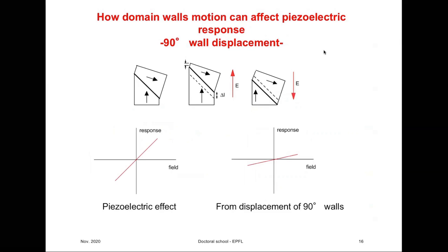Well, I'm exaggerating a little bit here the deformation of the crystal. The two domains are never at exactly 90-degree angle between polarizations. It comes from geometry, I'm not going to go into that. You have seen the pictures that I have given before of high, atomic resolution domains, and you will see that the angle is not exactly 90 degrees, but a little bit smaller, I think about half a degree.